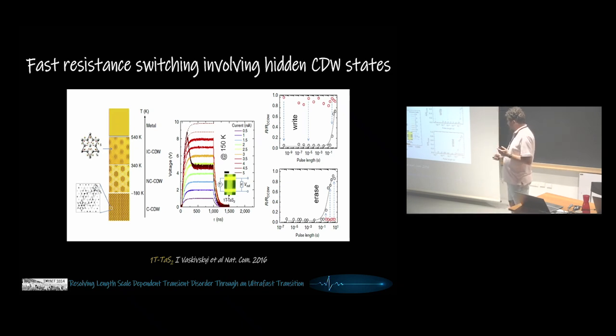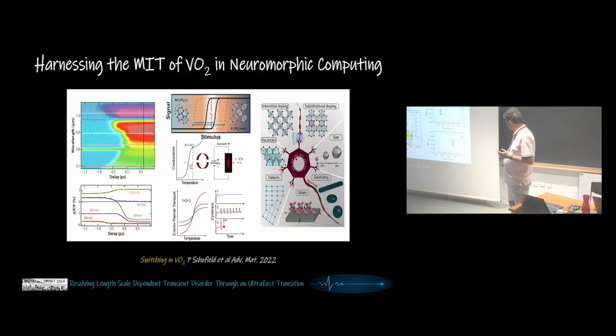And then in this particular system, it's a very famous charge density wave material. You have a cascade of first order phase transitions from a high temperature metallic phase to a low temperature commensurate charge density wave and everything in between. So this will become relevant for a question that I want to pose. Okay. There is also switching that you can achieve in vanadium dioxide based devices, and you can utilize various channels to control the properties to your liking.